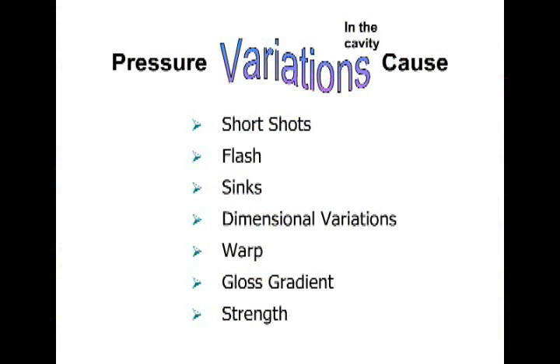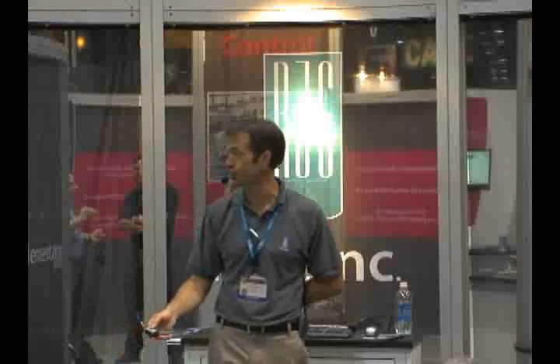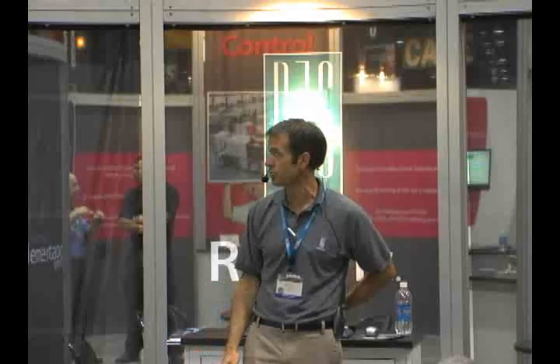Pressure variations inside the cavity of the mold have direct correlation to this entire list of issues: sink, flash, short shots, dimensions, structural integrity, gloss gradient. Depending on the application, you may do very well and improve your capability with pressure transducers.